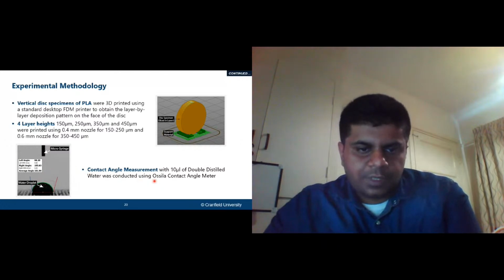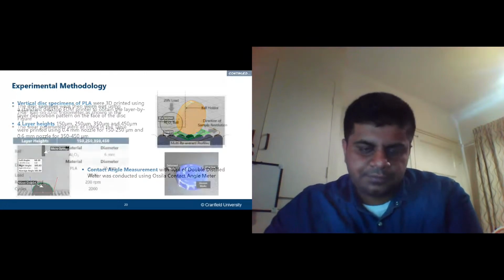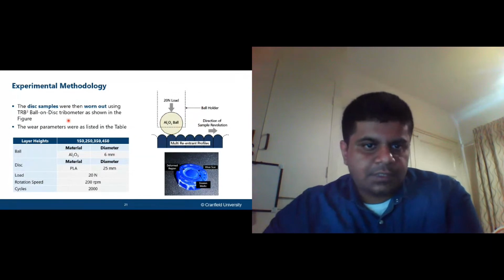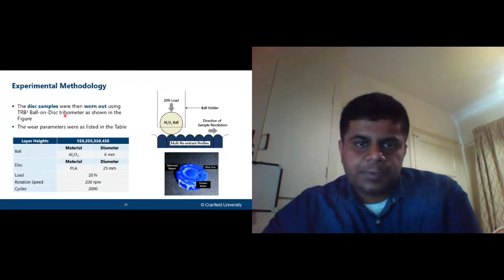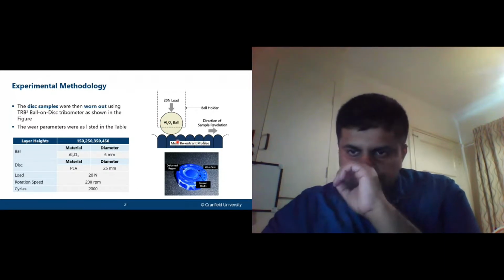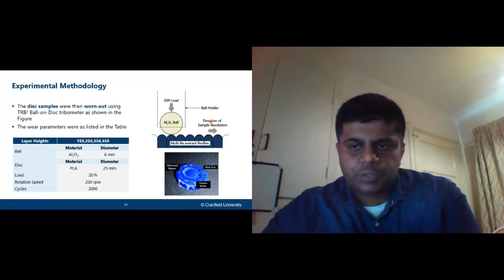And contact angle measurement, as shown over here, was conducted with 10 microliters of double distilled water using an Ossila contact angle meter. This is the tribological experiment that we conducted. We used this specimen that was burnished using a TRT ball fixture. So this is how the ball was oriented against the reentrant edge profiles. The sample was revolving this way, and the ball holder is basically applying a 20 newtons load.